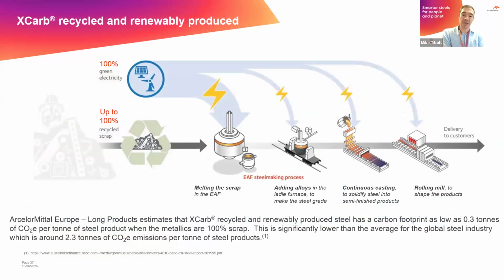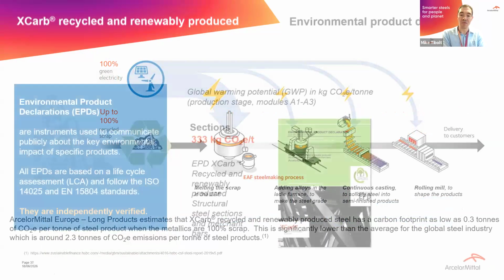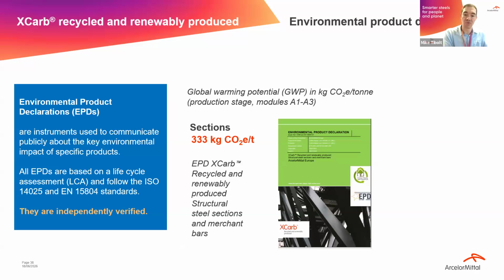X-carb means that the steel is produced in an electric arc furnace using up to 100% green electricity and up to 100% recycled scrap. And by doing so, we can reduce the carbon footprint of the product significantly. As you can see here, for the hot rolled sections, for instance, we have an EPD for modules A1 to A3 with a global warming potential of 333 kilograms of CO2 per ton of steel produced.